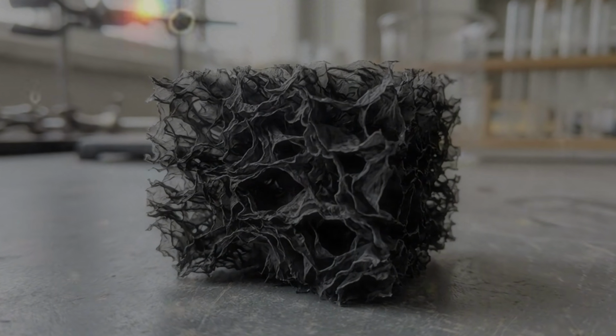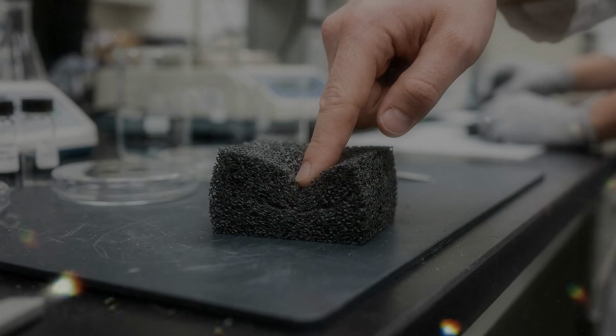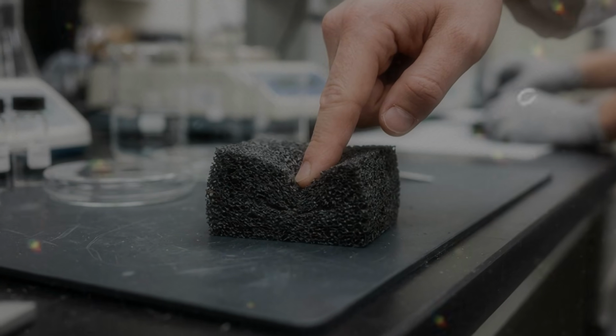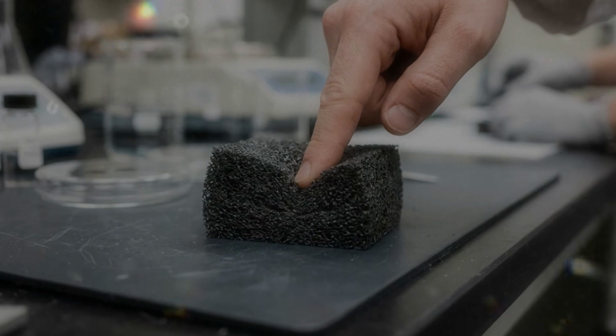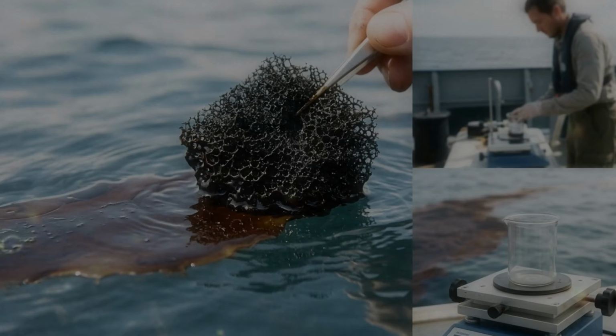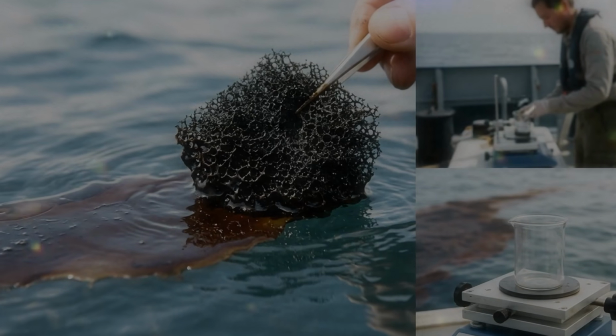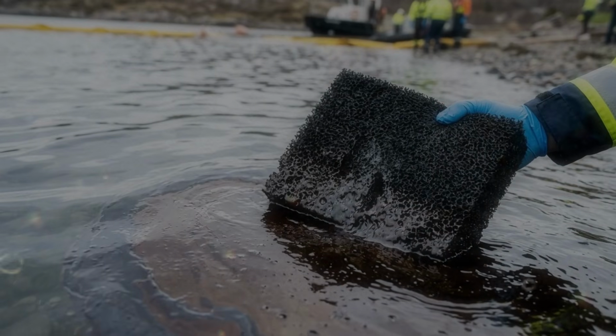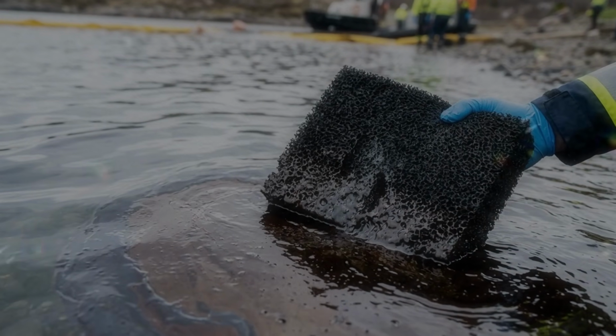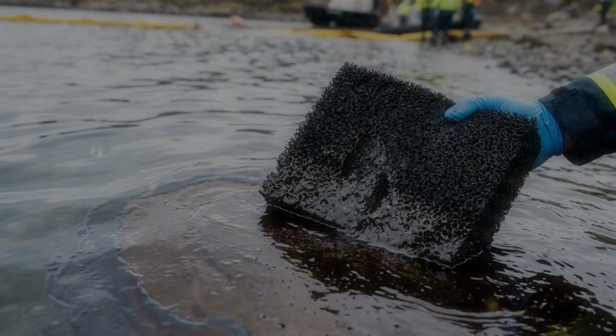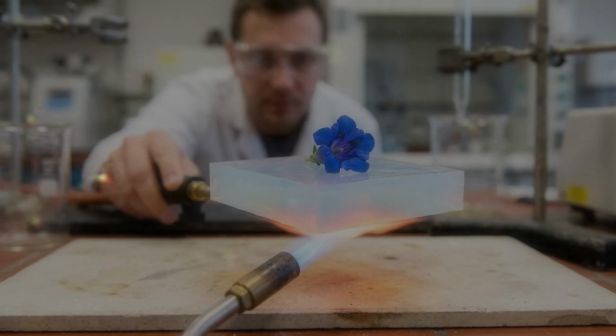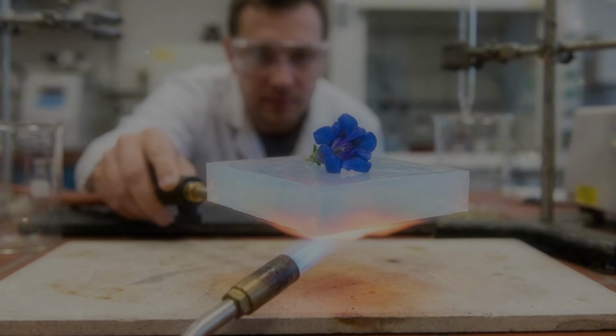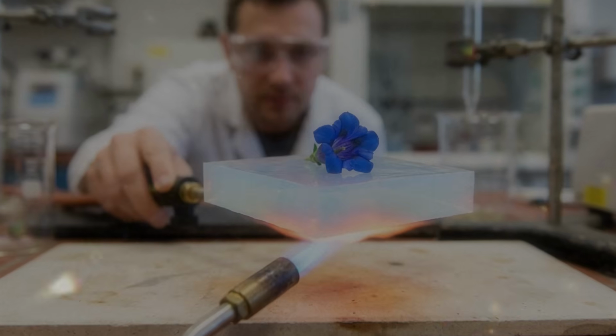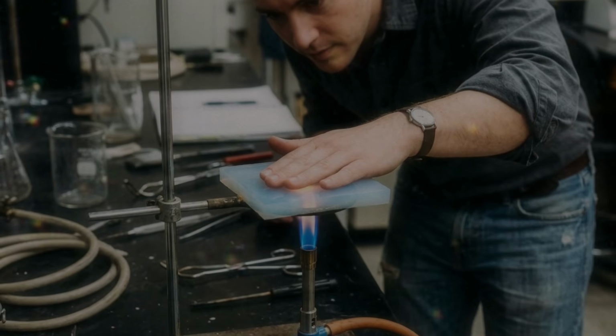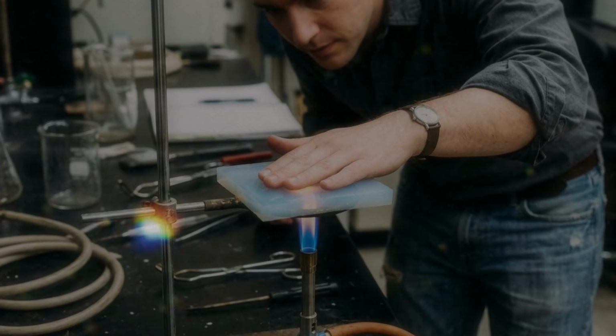A reinforced sample may lose the right to call itself the lightest, yet gain the ability to become a sensor, an electrode, or an absorbent used more than once. The absorbent behaviour provides another example of strength through structure. Graphene-based aerogels can take in oils and organic liquids throughout their open pores. A sample may absorb many times its own weight, because its own weight is extremely small and its internal volume is large. After absorption, the situation changes.